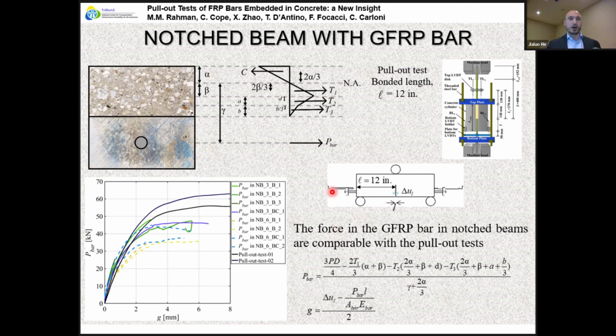If you basically plot the load in the bar and half of this opening, which is the slip of the bar, in this plot, and you plot it together with the load in the bar and the slip of the bar from a pull-out test, you see an interesting thing: for the very first part of the response here, up to 35 kilonewtons, which is the service load, you can actually get a match between a pull-out test and this test with the notched beam.